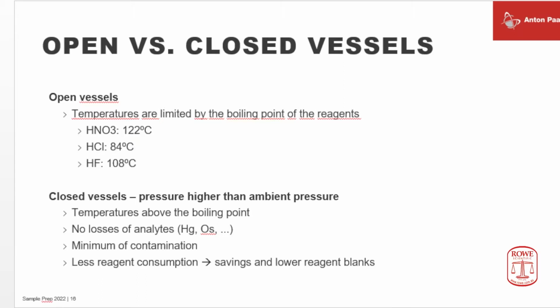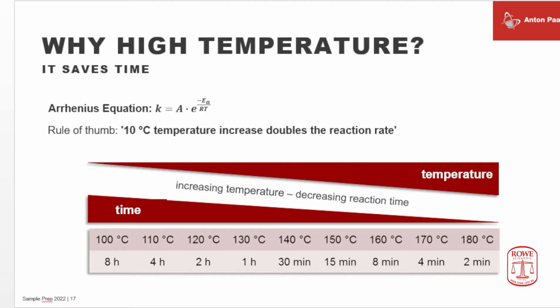Why do we want high temperature? Of course, for saving time and for the sake of completeness of the reaction. So the higher the temperature, the lower the time consumed to complete the reaction. This is expressed in the Arrhenius equation, as we chemists know. Expressed as a rule of thumb, it means a 10 degree increase in temperature will double the reaction speed. What that means is, for instance, a reaction that would take 8 hours at 100 degrees could be completed within 8 minutes when we can take the same reaction to 160 degrees. So it's simplification, time reduction when we can work in systems allowing higher temperature.